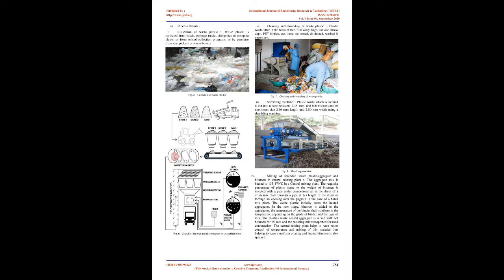Manufacturing of bituminous mix using waste plastic: Bituminous hot mixes using waste plastic for road construction are manufactured using either a dry process or a wet process. The dry process is considered to be simple, economical, and environmentally friendly, while the wet process requires more investment and machinery and hence is not commonly used. The scope of the present guidelines is restricted to the dry process only. Plastic is coated over stones, improving the surface property of aggregates. The coating is easy and the temperature required is the same as road laying temperature. Waste used should be 6-8% by weight of bitumen depending on climatic conditions.